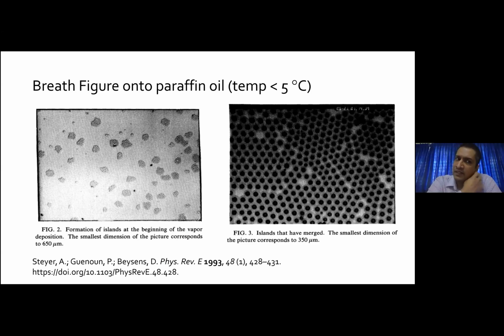For this, the group used paraffin oil. Paraffin oil at very low temperature is almost a soft material, and it is hydrophobic in nature. And when you try to condense the water droplets onto this hydrophobic thin layer, the hydrophilic water droplets tend to push away these hydrophobic oil droplets.